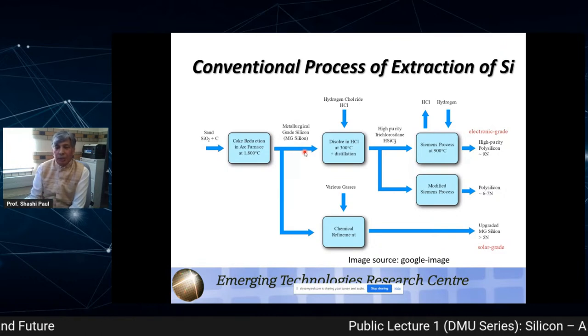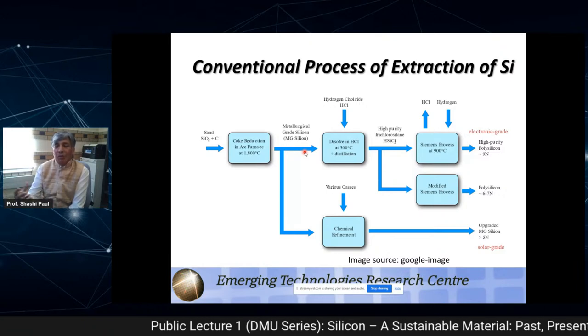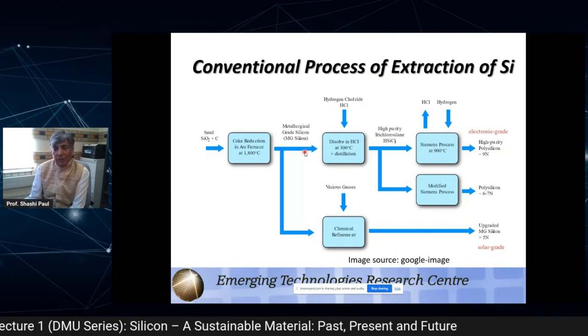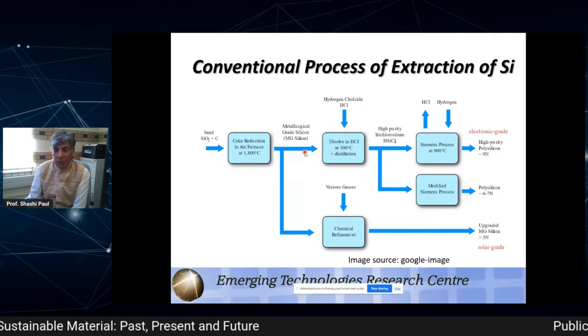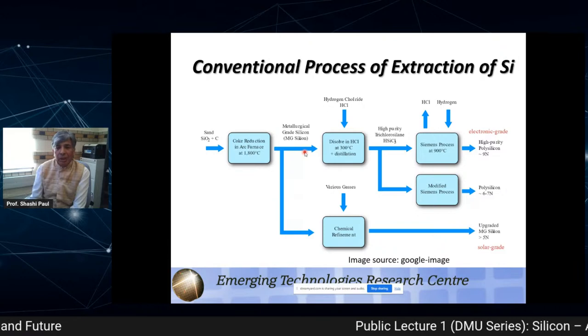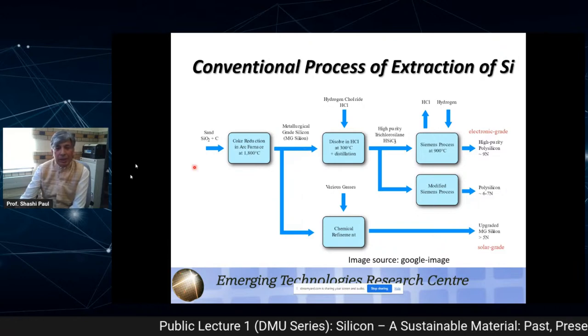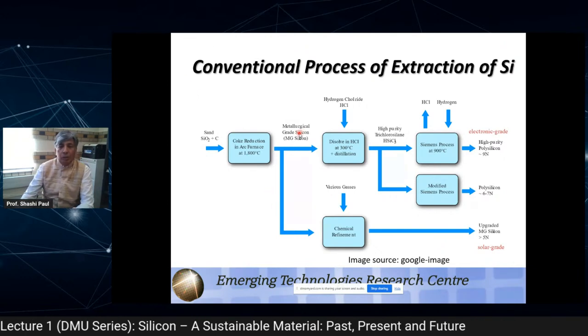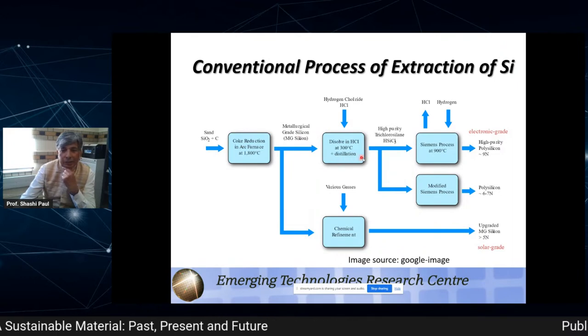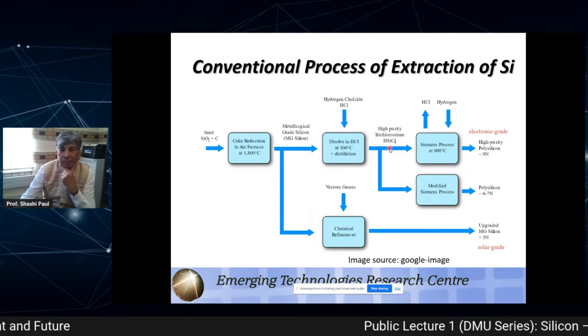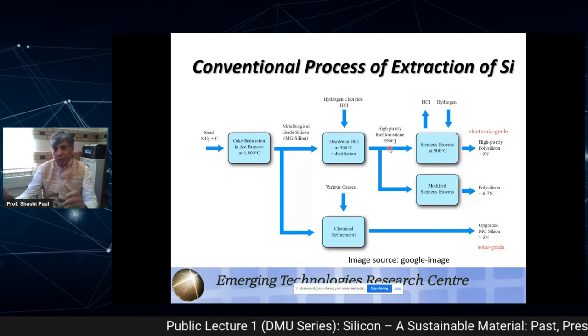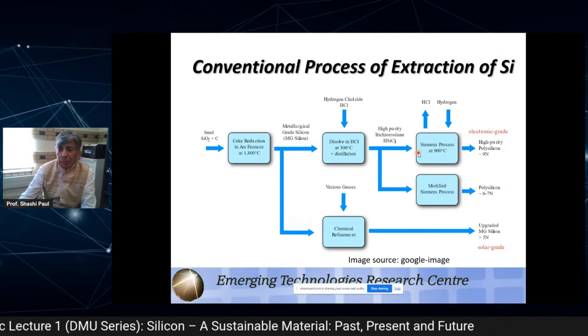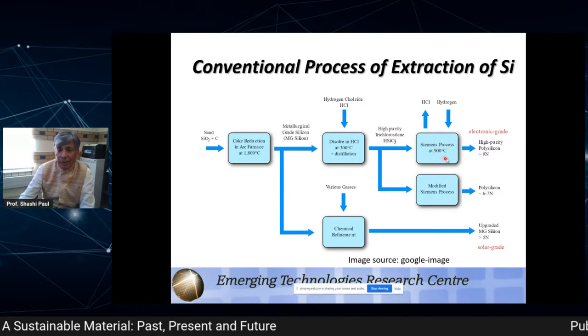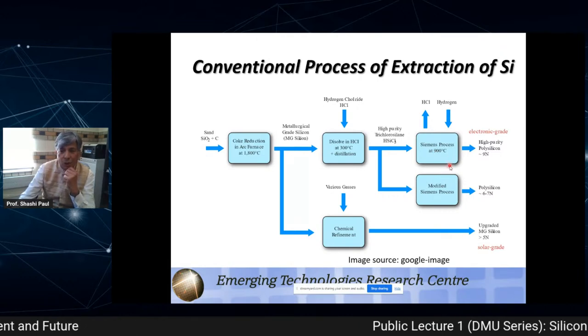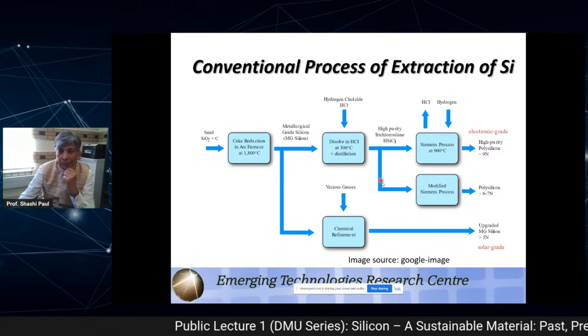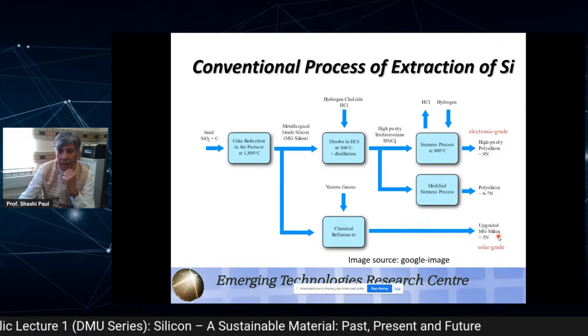I tried to show you in my previous slide that doping or unintentional impurities can lead to a curse, meaning that you won't have control over the resistivity. So it is not very pure silicon. Some impurities are still there. It can have iron and many other things, the natural material already present in the sand, which end up in this grade of silicon as well. Then it is dissolved in HCl, and you create trichlorosilane gas, which is quite a nasty gas, but it is properly confined. Then you use a process called the Siemens process at around 900 degrees centigrade. Again, you can notice it is quite a high temperature. And then, whatever route you take, the next step gives you a higher grade of silicon.